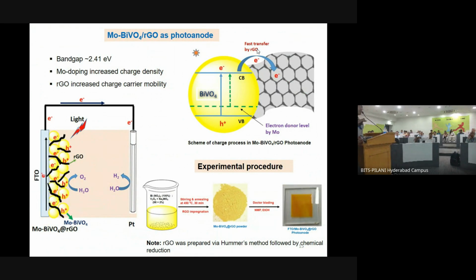But so far, as I mentioned, this was once again noble metal based. If you really want to look for non-noble combinations, then we look for something else. Finally we went to bismuth, which I will also tell you. Bismuth vanadate is known as a material which is inferior, which cannot liberate hydrogen. It can only act as a working electrode. So it cannot do the hydrogen evolution reaction, which means what you are looking at is basically the current due to the oxidation part of it.